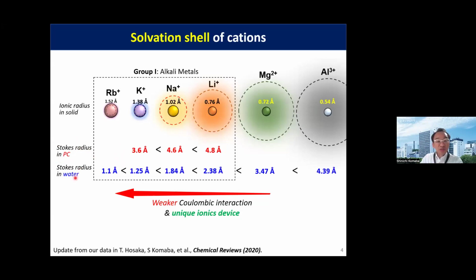Of course, in the case of aqueous solution, we have a Stokes radius for each alkali ion with its hydration shell. As you can see here, in the case of magnesium and aluminum ions, the solvation shells are much larger than for alkali metals. In the case of lithium, it is the biggest, showing the biggest Stokes radius compared to sodium and potassium. And among the alkali metals, we have the smallest Stokes radius for rubidium.